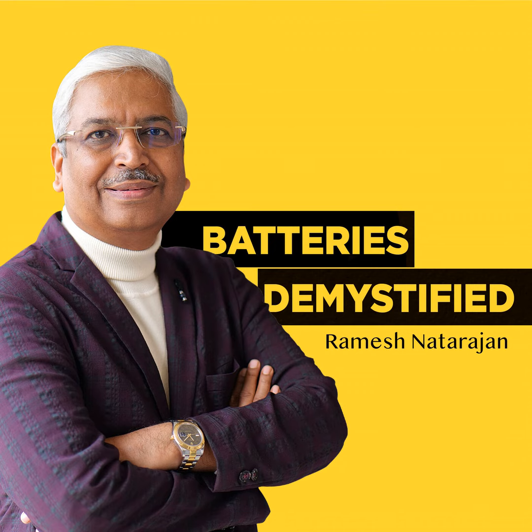I shall discuss the use of cadmium as a neutral electrode in this episode. Cadmium is a metallic element that has a resemblance to zinc. Cadmium is inherently hazardous and is classified as one of the metals that have a significant impact on public health. Cadmium serves as a neutral electrode to identify the cause of failure in a lead-acid battery cell. It specifically indicates whether the failure of the battery is due to positive active material, negative active material, or electrolyte deficiency. In the design of lead-acid batteries, cadmium is employed to identify the specific electrode that is causing the battery to underperform during the last stages of discharge.